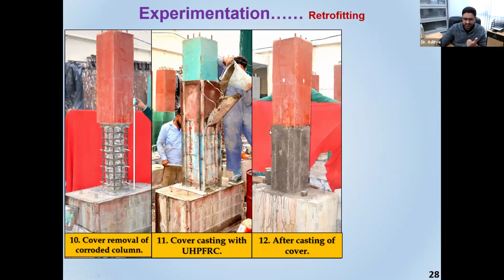You can see neither its weight has increased, nor has its cross-sectional size increased. So there's no increase as such. But at the same time, we have applied at least one layer of retrofitting, which is only using UHPFRC. Now, we will examine this specimen in the same testing setup and compare it with the normal 10% corroded column and the 0% corroded control column. We'll examine whether the load capacity and the ductility are good enough, and all those things, with the help of those 8 indices that we have calculated.